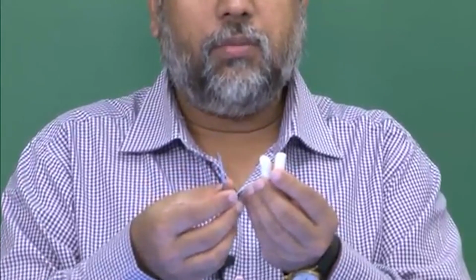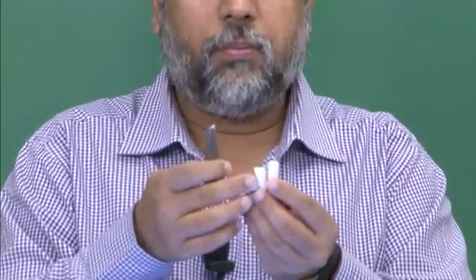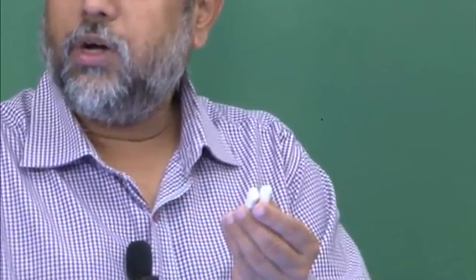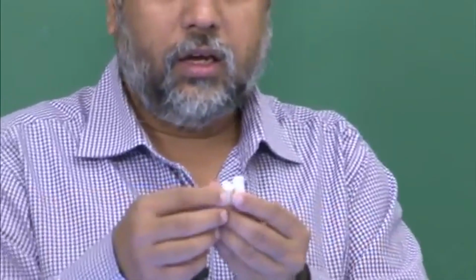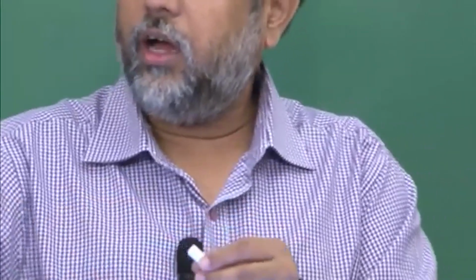So, you can consider these with respect to the ductile failures that happen in a metallic sample. You can see that, much unlike the ductile failure, the brittle failure is much different. There is no necking, it just falls apart, and not only that, the stress at which it falls apart, if I take another chalk sample, you may actually get more resistance to failure. So, it varies from sample to sample. That is the point I wanted to stress.